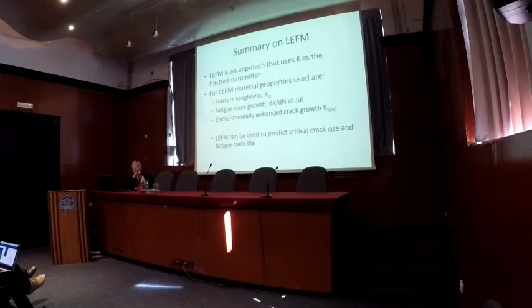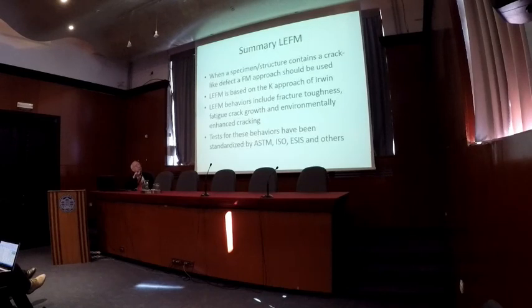And in summary then, linear elastic fracture is an approach that uses K as the parameter. I might not have said this, but LEFM stands for linear elastic fracture mechanics. We use LEFM a lot. In LEFM, we worry about fracture toughness through K1C, we worry about fatigue crack growth, the da/dN versus delta K, and we worry about environmentally enhanced cracking. And you can use then the LEFM approach to get critical crack sizes and fatigue life, which gets into applications.